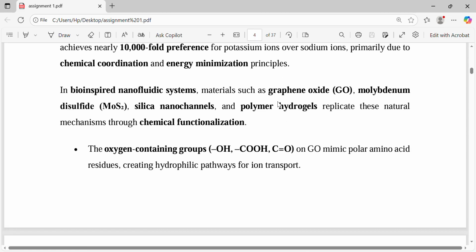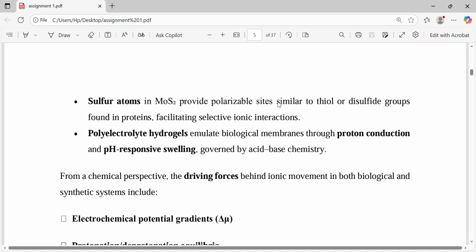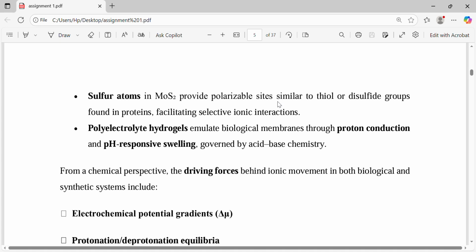In bio-inspired nanofluidic systems, materials such as graphene oxide, molybdenum disulfide, silica nanochannels, and polymer hydrogels replicate this natural mechanism through chemical functionalization. The oxygen-containing groups mimic amino acid residues, creating hydrophilic pathways for ion transport. Sulfur atoms in MoS2 provide polarizable sites similar to the disulfide groups found in proteins, facilitating selective ion interaction.